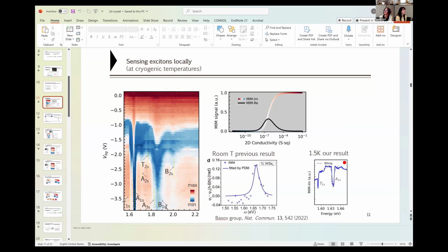What we found from some of these measurements was that we didn't see too many so-called charge puddles that create a lot of problems in the inhomogeneity of the gating profile in space, which was pretty good actually. But if you put it in air and oxidize it for some time, then it will become worse. That's also what we found. For the other oxides, if you have great candidates, I would love to talk to you.